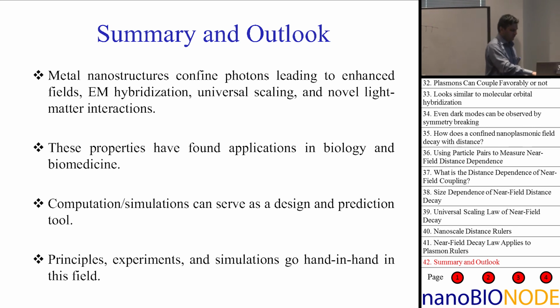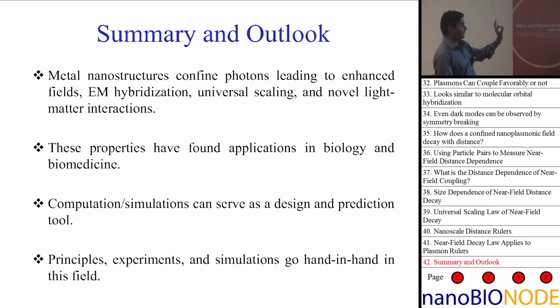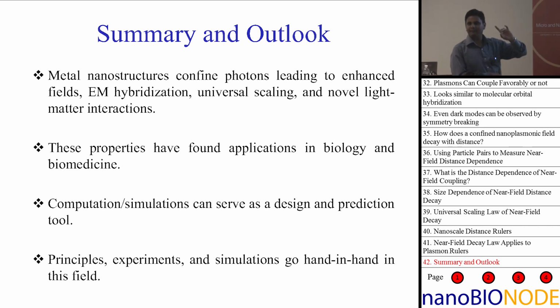Okay, and this picture should still hold. You should see four modes. There you go, I skipped that example. Not fancy shapes, but two different sizes. Dissimilar sizes. Now the dipoles are opposite, but they are not equal, and they don't fully cancel out. So you'll see four modes. This is on a single dimer, by the way. This is on the same dimer that I told you we were able to sense a single DNA strand from Raman. You see four modes.